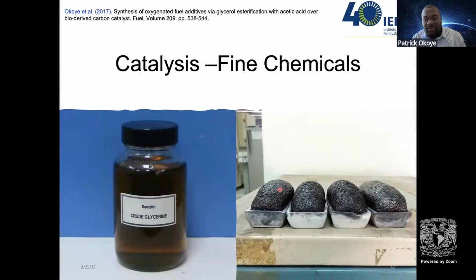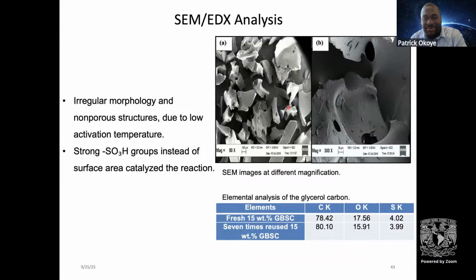So usually we produce this, and I always call it glycerol bread. But it's not edible. You cannot eat this. We produced this, and this is how it is. This material is dense. It really does not have surface area, and it has very irregular morphology. However, it is rich in sulfonic groups, which is necessary to catalyze our reaction.